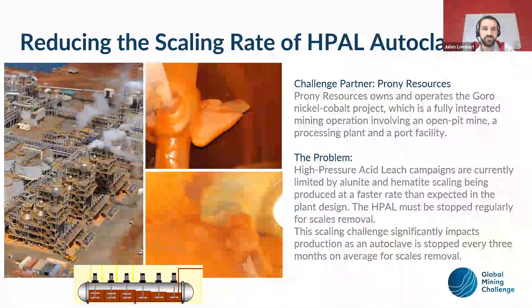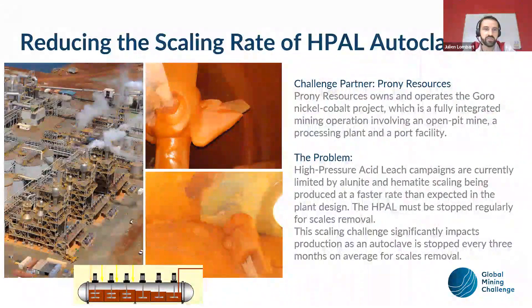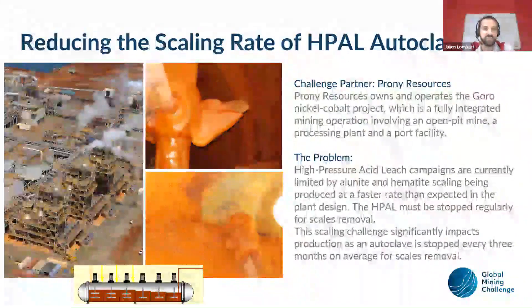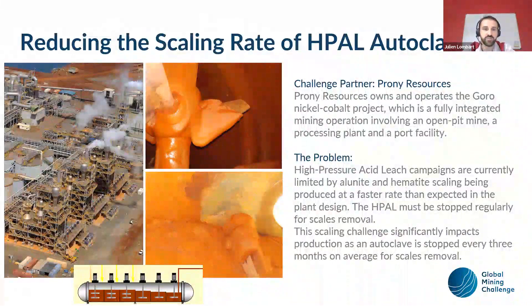This kind of crust of scales can be very thick, especially in the first compartment where we add the sulfuric acid. We create a thick scale that can reach 15 centimeters in the worst case in the first compartment, which is beginning to be a huge scale.